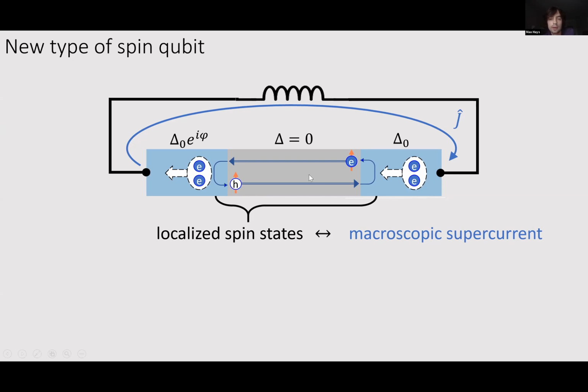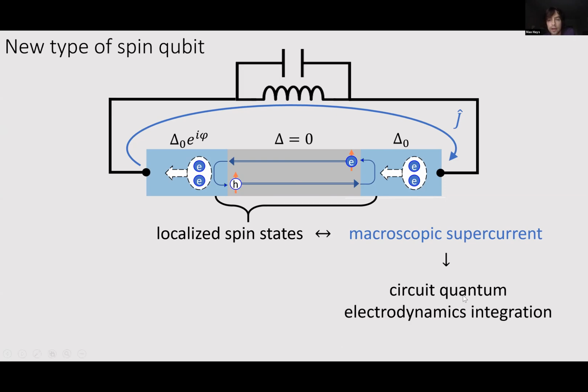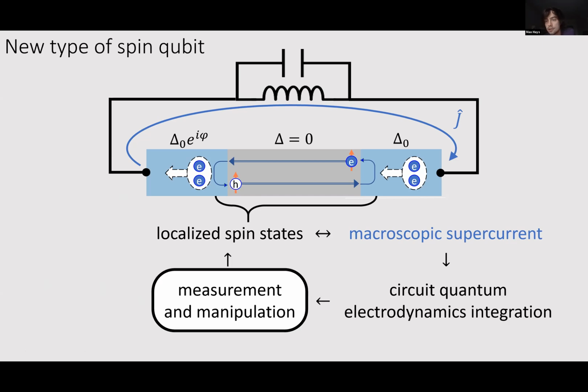So here I'm showing the weak link embedded in this flux loop, and this current J can flow around the loop. So even though we have these localized spin states, we have this macroscopic supercurrent that we can couple to. Then we can imagine putting a capacitor in parallel with this inductor, and then we have a resonator, and we can probe the system using circuit QED. As we saw again in the last talk, this is an extremely powerful platform. So we have these localized spin states. They give rise to macroscopic supercurrent, which lets us couple in via QED, and this can let us do measurement and manipulation of these spin states in new ways.